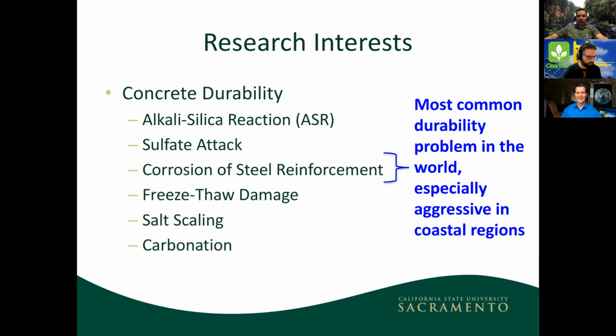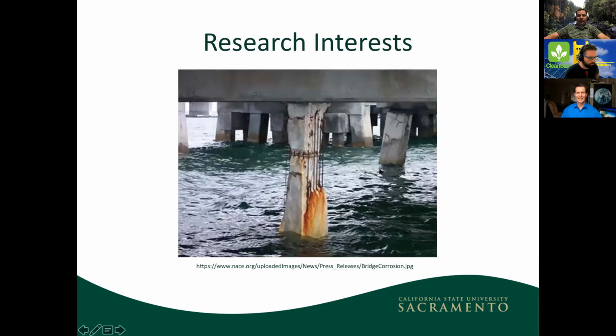Corrosion is the number one headache for concrete in the entire world. Ironically enough, this is not a problem in the concrete. This is a problem in the steel that's required to reinforce the concrete. The steel doesn't want to be steel. It wants to be iron oxide. So eventually it turns back into iron oxide over time. Concrete does help in that it's a lot harder for the steel to corrode, but it is going to happen. And it can get severe enough to look like that. It's very aggressive in coastal regions. It's also very aggressive in colder climates, like in the Sierra Nevada region.